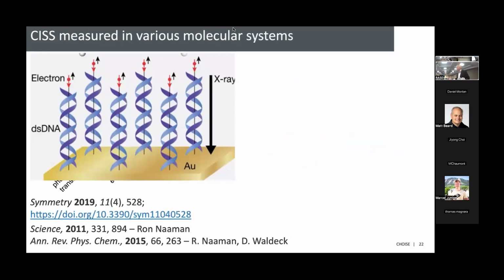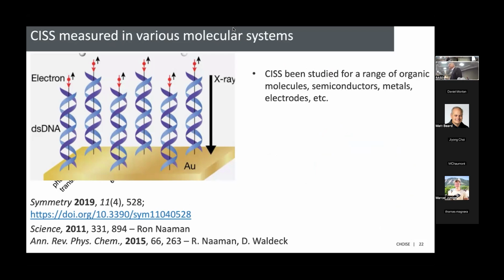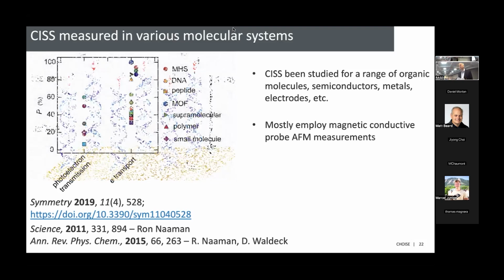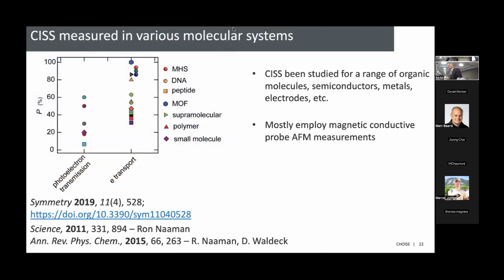So as I mentioned, it's been measured many times. This is Ron Naaman and David Waldeck, and they were basically taking gold or something with oriented chiral molecules and then passing electrons through them. And then depending on the chirality of the molecule here, they would get preferential transmission of up or down spins. So it's been studied for a range of systems, mostly employing this magnetic conductive probe AFM measurement, which I'll mention in a minute. But there's now all kinds of measurements of this.